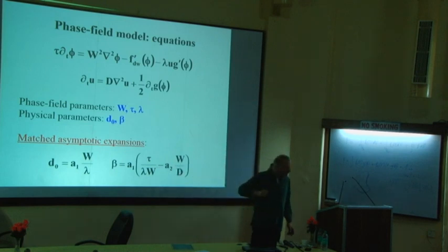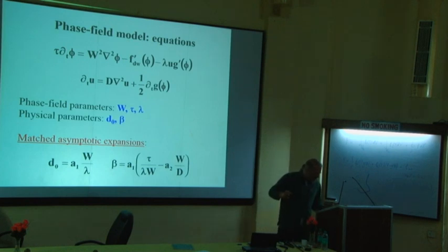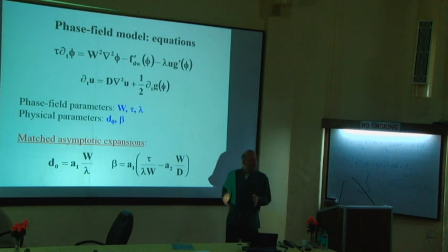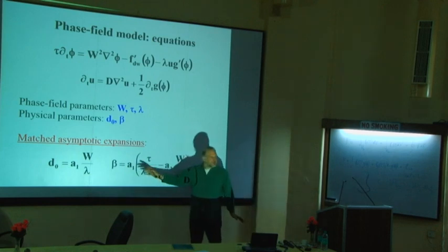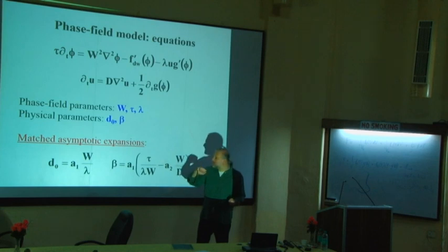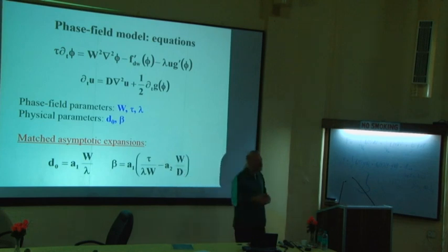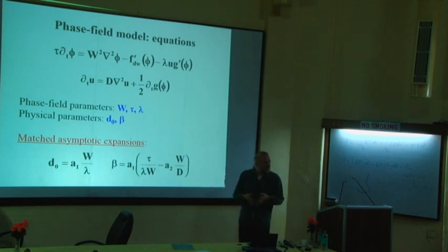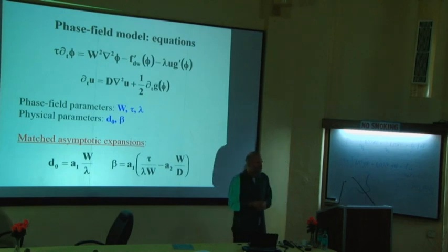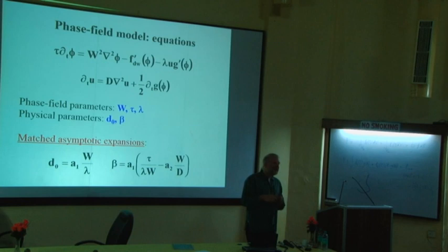And so in the high undercooling limit, actually, so I have told you, in metallurgy, for slow solidification, beta is approximately 0, or the interface mobility is approximately infinity. Now, if you go to very fast solidification, like for the nickel dendrites, then this is not true. Beta has a finite value, and it's important to know the interface mobility. Now, it's really very hard to know the interface mobility from experiments. So what we did is we collaborated with people who did molecular dynamics simulation. So they did molecular dynamics simulation of nickel interfaces, so the growth of nickel dendrites in pure nickel.